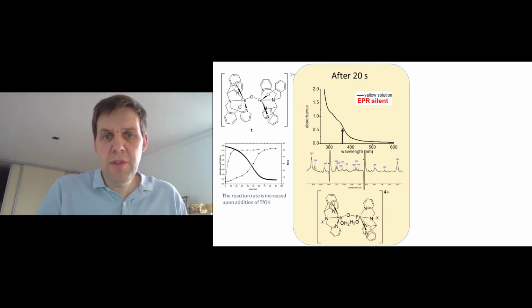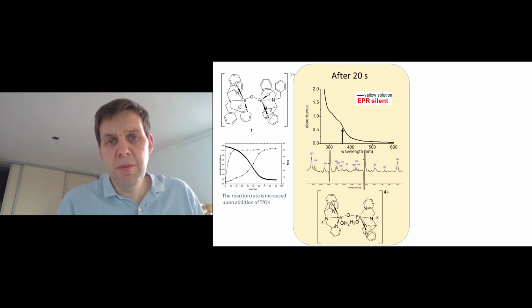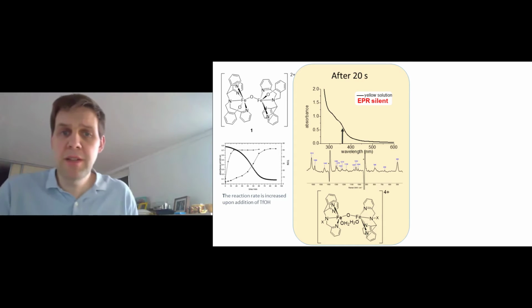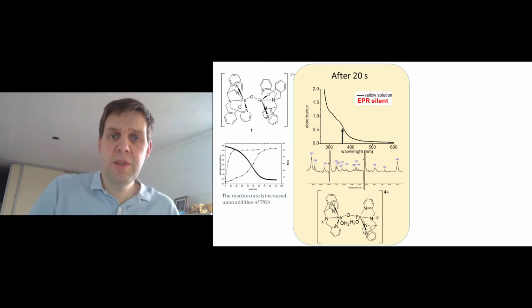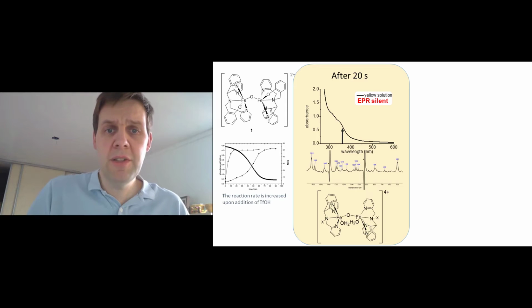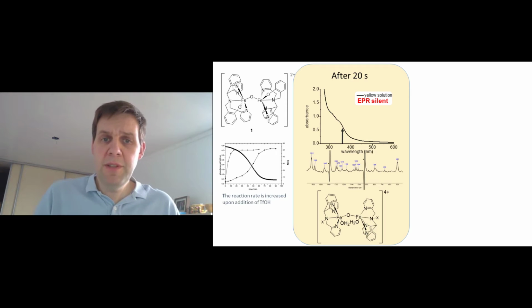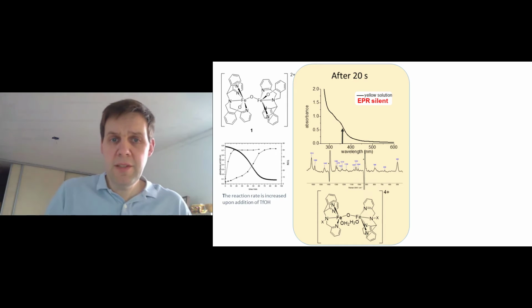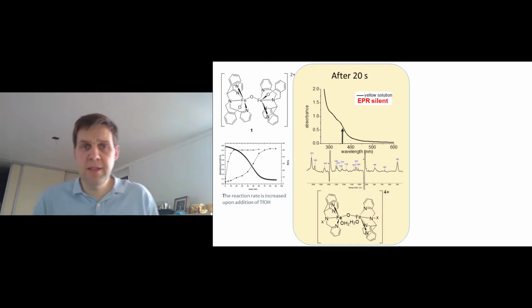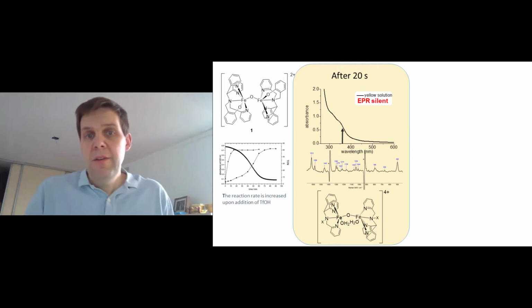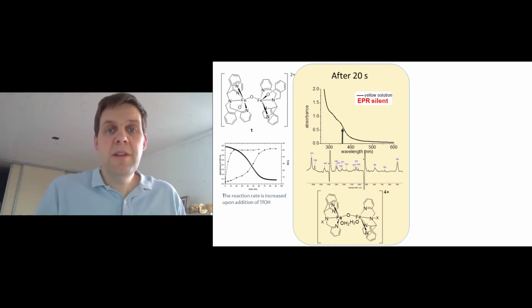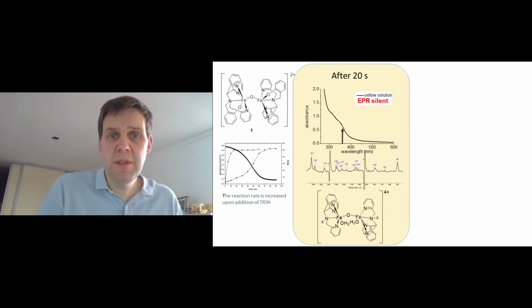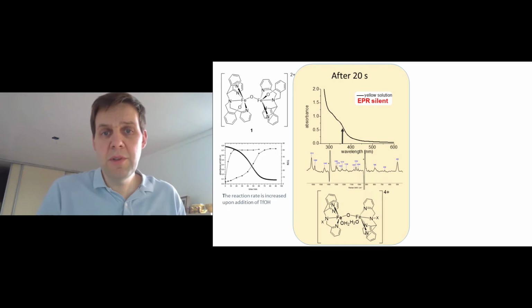Well, one trick is to use a technique called resonance enhanced Raman. So we run a Raman spectrum with an excitation which is resonant with an absorption band. And I'll come back to this a lot. Because of that, even something present at a very low concentration, there's a chance that its Raman modes will be enhanced quite dramatically. Sometimes you hear quotations of 10 million times, but in the case of inorganic compounds, it typically is 50 to 100 times enhancement, which is just enough to get a 1 millimolar solution of something up to the level where you can start detecting.